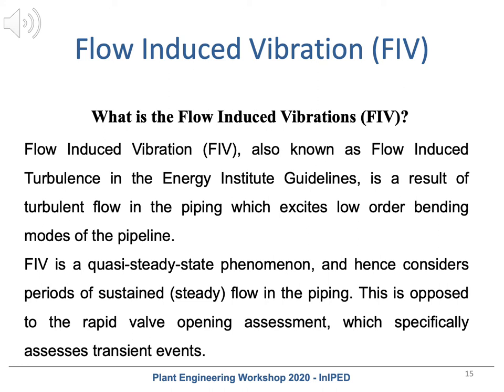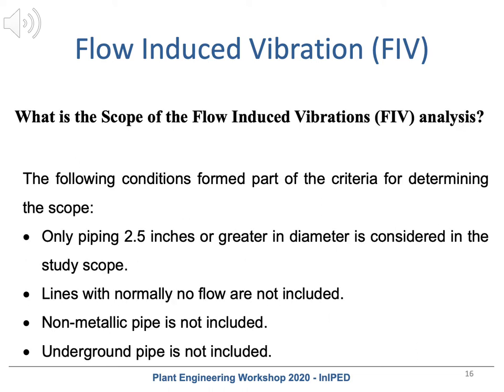Piping with high stiffness, as measured by the fundamental natural frequency, is more robust to flow-induced vibration failure, as excitation levels decrease at increasing frequency. The scope of the flow-induced vibration studies covers the assessment of risk due to flow-induced vibration. It doesn't include the assessment of vibration generated by other mechanisms, for example, compressor pulsation, mechanical vibration, and vortex-induced vibration.